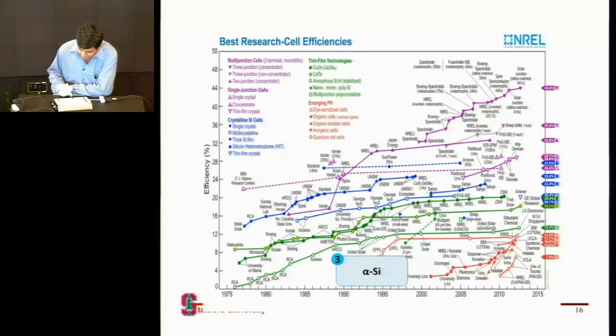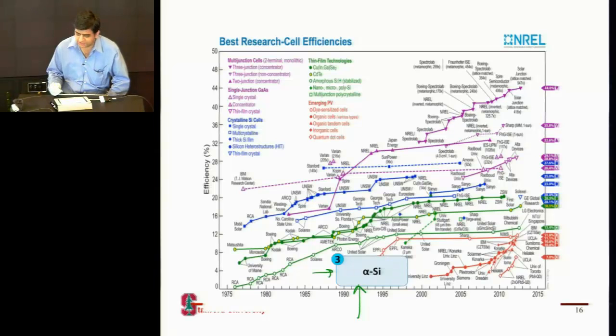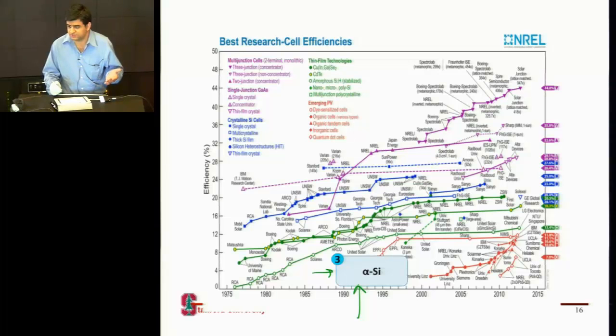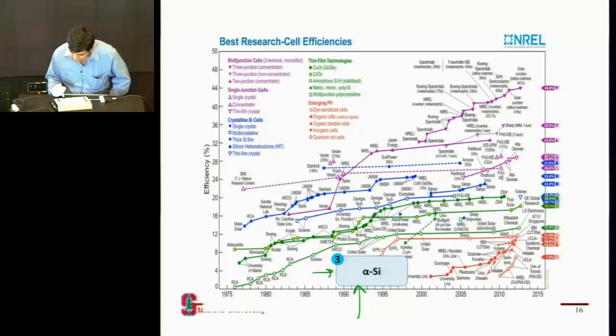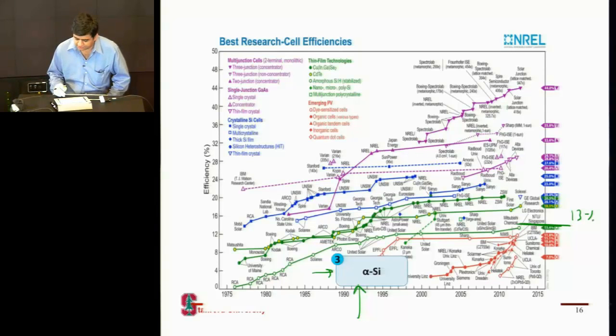What we now know is amorphous silicon is not a very good candidate, though there was a lot of excitement about it from around 2007 to 2010 when polycrystalline silicon prices were up. A lot of people were interested in amorphous silicon because it has a much higher absorption coefficient, so you can use a much thinner amount of material. But the efficiencies of these cells never exceeded 13% even for champion lab devices, and it has a plethora of other problems.